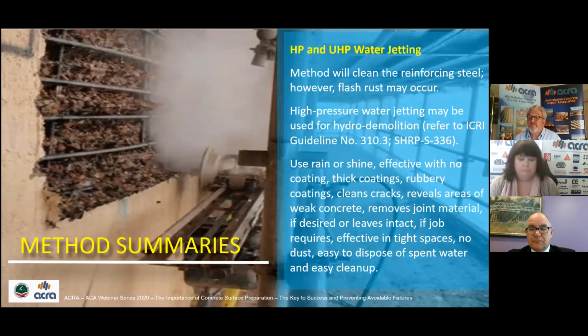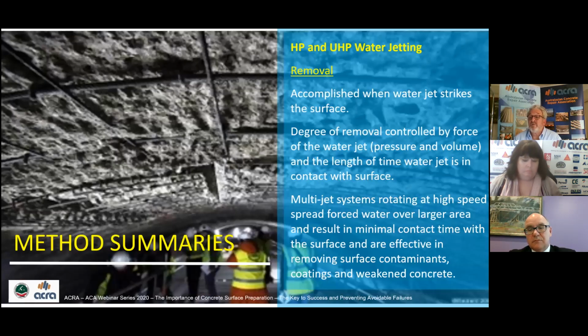Effective on horizontal and vertical surfaces, effective with no coatings, thick coatings, rubbery coatings, cleans cracks, reveals areas of weak concrete, removes joint material if desired or leaves it intact, and if the job requires it, can be effective in tight spaces. No dust, easy to dispose of spent water, and easy cleanup. Removal is accomplished when the water jet strikes the surface. The degree of removal is controlled by the force of the water, pressure and volume, and the length of time the water is in contact with the surface.